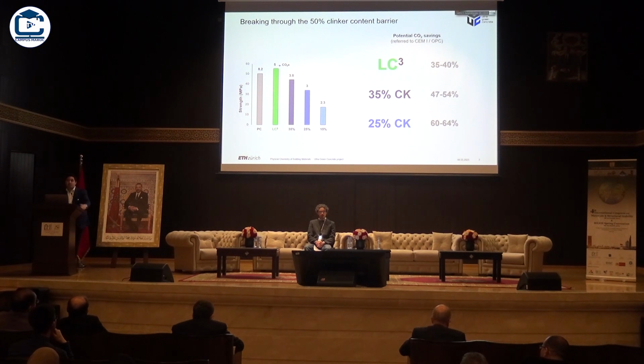If we go to something like 25% clinker, we can save between 60 and 64% CO2, referring to CEM I, to OPC, and assuming that we are replacing the clinker with a combination of calcined clay and limestone. But the strength is also going down. So the question, does it really make sense to do this, is not obvious.